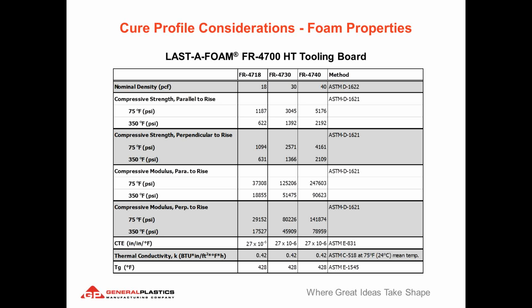But you can see the CTE is really the same for all 3 densities of material. And that's due to the resin system being identical for all those materials, so the resin will expand at the same rate. The only difference between these materials is just the amount of air or gas inside them. And these are all materials that do not outgas, by measurements of the thermogravimetric analysis.